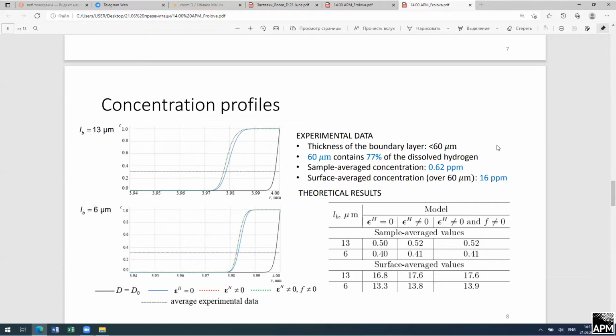Also, I should note that according to experimental data, 60 micrometers contains about 77% of dissolved hydrogen. However, here we obtain that our boundary layer contains all dissolved hydrogen. So further investigations are necessary to describe a deeper diffusion process. At the same time, values of sample average concentration and surface average concentrations obtained experimentally coincide with our theoretically estimated data. So our model describes the real experiment not only qualitatively but also quantitatively.